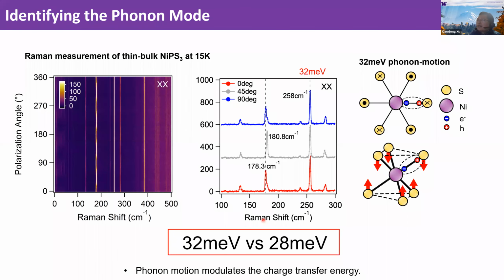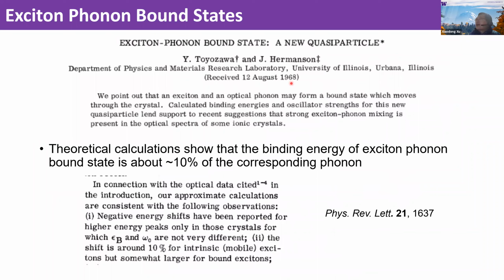Then we went back to the literature again, and many years ago, back in 1968, there was just a theory paper. The title of the paper is Exciton Phonon Bound States, a New Quasi-Particle. So basically, we have excitons and optical phonons. We know optical phonons carry dipoles, right? They are polarized. So the exciton and the optical phonon actually form a bound state, and this is called an exciton phonon bound state. The exciton phonon bound state has also been measured in many ionic compounds, and from empirical measurements and calculations, it shows that the binding energy of these exciton phonon bound states is about 10% of the corresponding phonon energy.